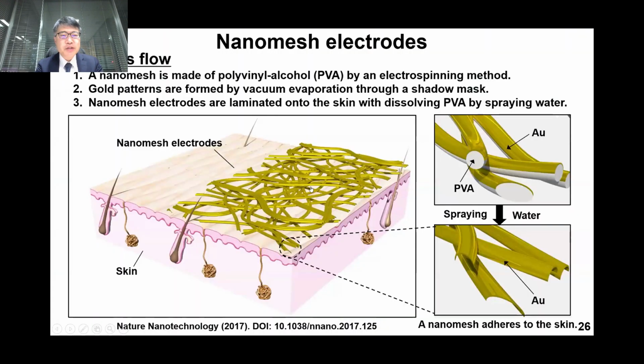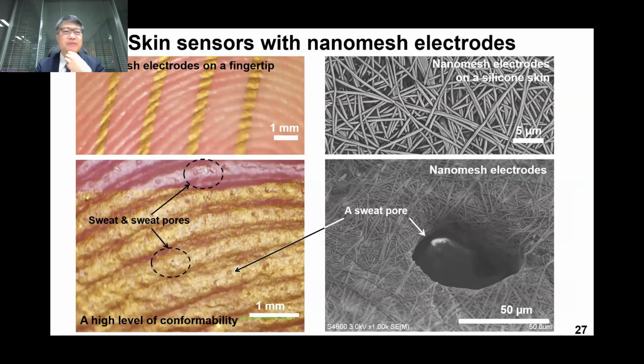So let me show you the device fabrication. The nanomesh is made of polyvinyl alcohol, which is known as a water-soluble polymer, by the electrospinning method. And gold patterns are formed by vacuum evaporation through a shadow mask. The nanomesh electrodes are put on the surface of the skin and some water is applied by spraying. The PVA is dissolved by water and washed away completely. Finally, a breathable porous gold thin film remains on the surface of the skin.